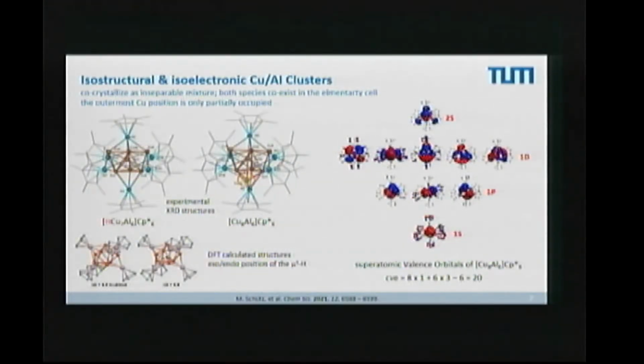Why superatom? Because the shape and the symmetry of the molecular orbitals of these clusters emulate, so to say, what we know from the hydrogen atom. And the energy sequence is different. So in the hydrogen atom, we would have s, p, and then again s, p, and then d. But we have here, because of the different situation of the distribution of the nuclear charge over a finite volume, a different sequence of energies. But the symmetry is the same.